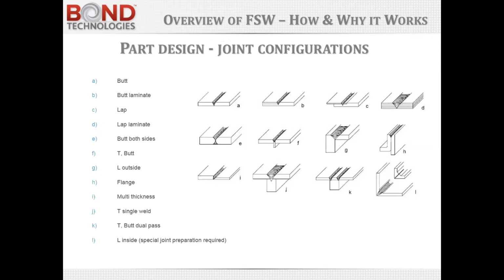Joint geometries are shown in this slide that are kind of popular. Some joints work better than others, but one of the things to be careful of is because of the high forge force and the high level of plasticity of the material, when a joint geometry is chosen, there needs to be very good support underneath. Let's take a look, for example, at joint J, which is a kind of a T-section. If the weld nugget were too large, you could imagine plasticized material causing a loss of containment underneath the flat horizontal plate. So in an example like this, one would use tooling to support that inside corner to avoid the plasticized material extruding down and out.